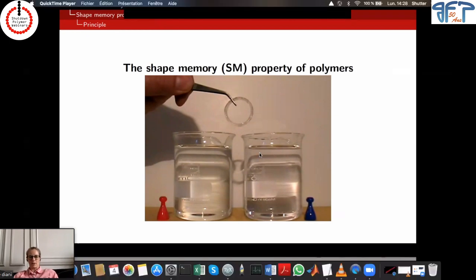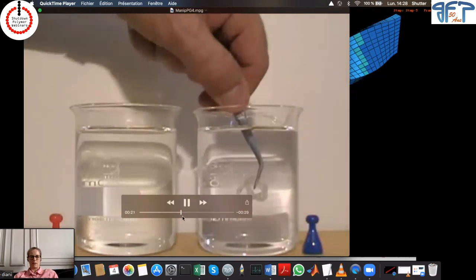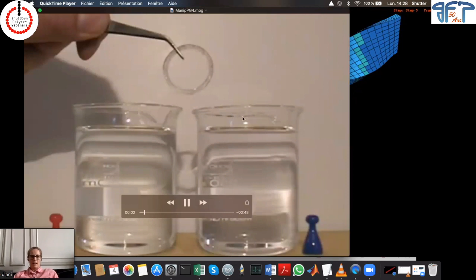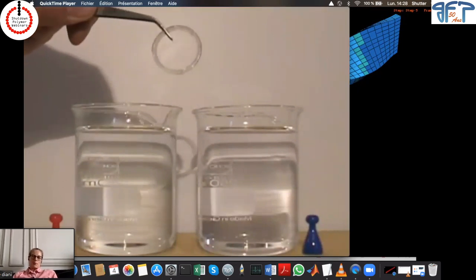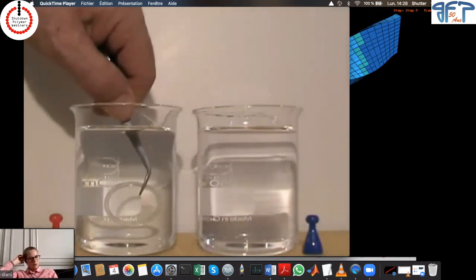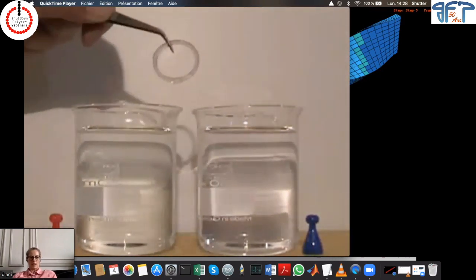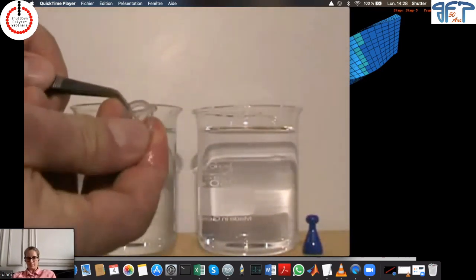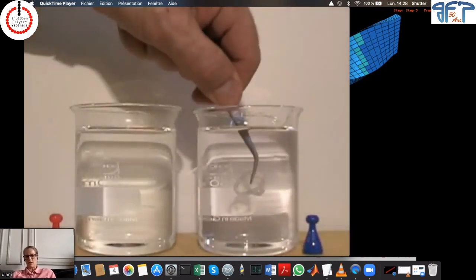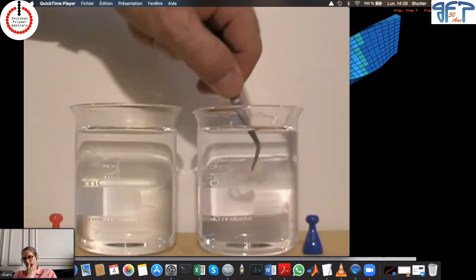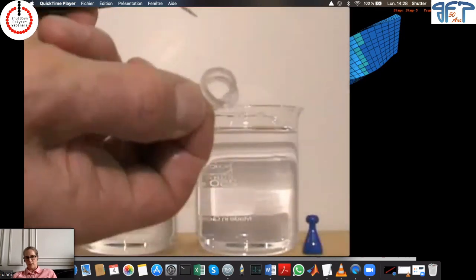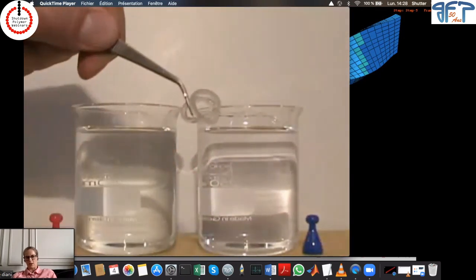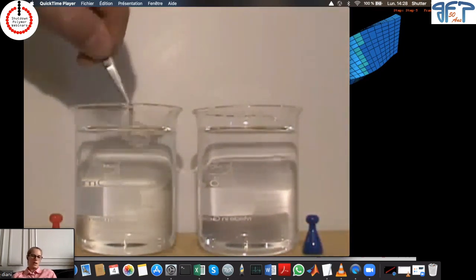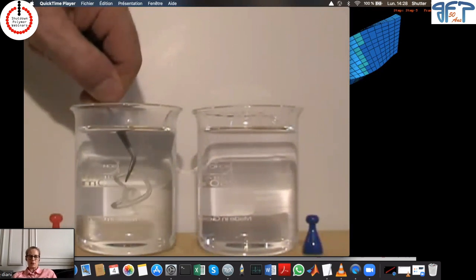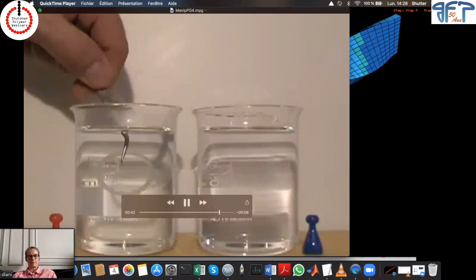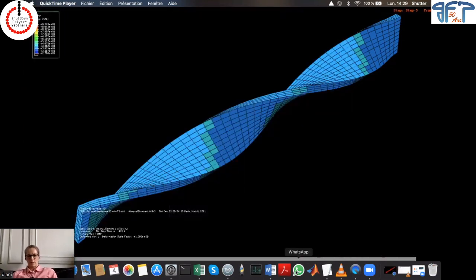So here you see a ring of amorphous network that we made of acrylate. Oops, I'm going to start from the beginning. And so the shape memory property for an amorphous network is very simple. You go at high temperature, you're in the rubbery state. In the rubbery state, you can apply large deformations that are reversible. So by maintaining the shape and cooling down the material, the material is in the glassy state, the chain mobility is very low, and so the material will keep its shape as long as we don't expose it to high temperature. If we put it to high temperature, it's going to recover the initial shape. Okay, I have to go back to my presentation.